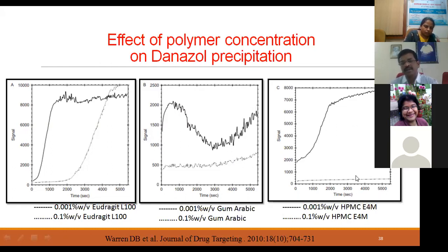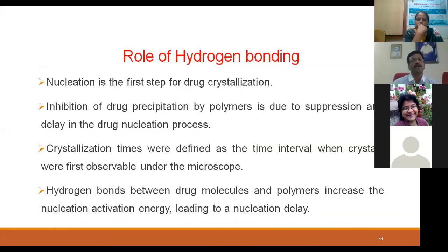See now, coming to the third polymer, HPMC, and here HPMC was taken in the two concentrations. Here, the concentration difference was not that much on the precipitation of the danazole. So from this study, we can understand that the three different polymers affect in three different ways, and the effect of one polymer will be different at two different concentrations, which is not similar to the gum arabic, which is not similar to the HPMC. So therefore, we have to carefully select the polymer, and we have to carefully select the concentration of the polymer.